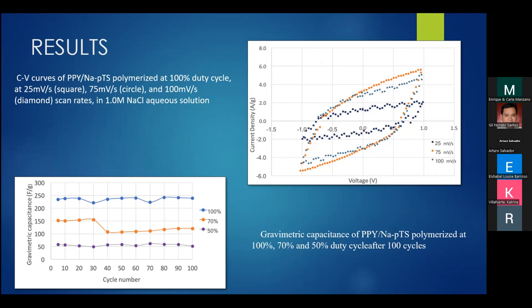And then we also did the cycle life test for the same film, the conducting polymer film grown at 100% duty cycle. We determined how its capacitance changes over time, over 100 cycles. Ideally, of course, you discharge your device more than 100 times. But over 100 times, the film grown at 100% duty cycle really did not deteriorate much as compared